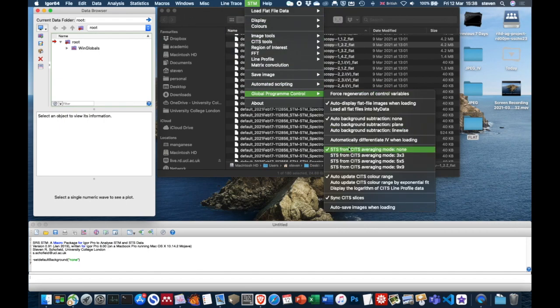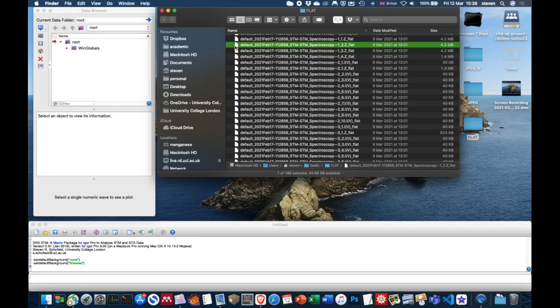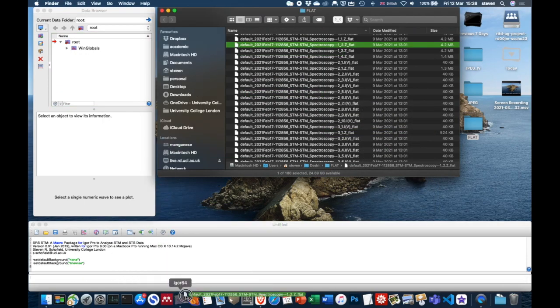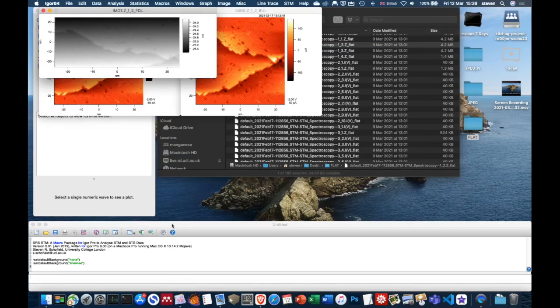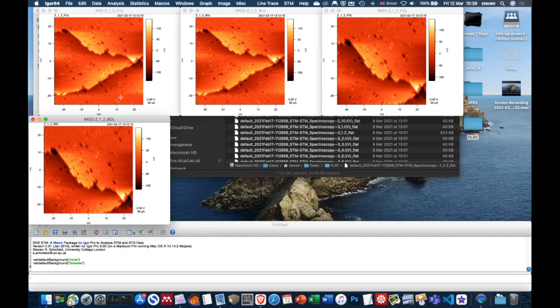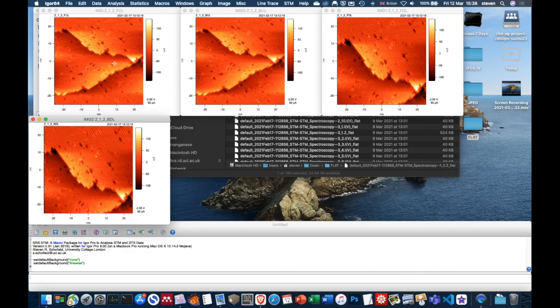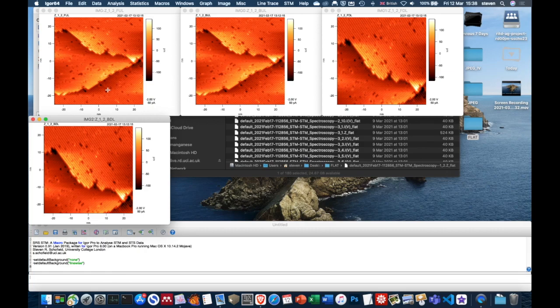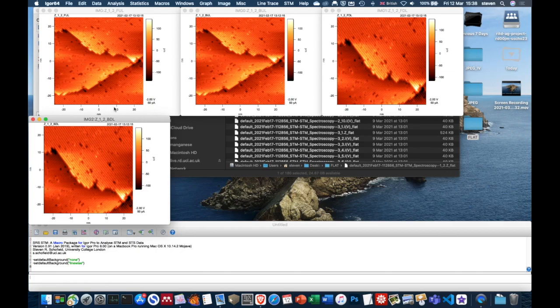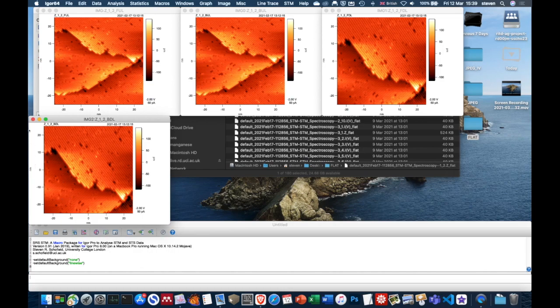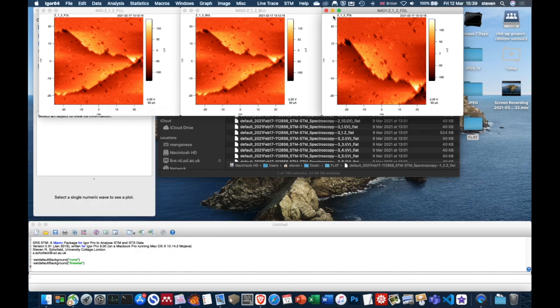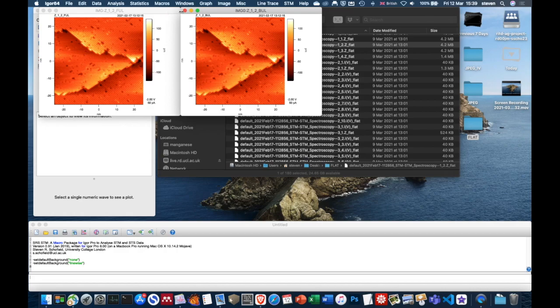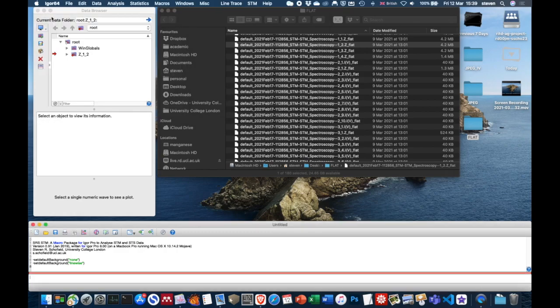Conversely, we could also have set that to global program control, auto background subtraction. If we make that line wise, then it will do a line wise subtraction on your data. And the thing about line wise subtraction is that it now introduces artifacts into the image. You can see that this little corner of the terrace looks like it's higher than the rest of the terrace. And that's just because what the program is doing with line wise subtraction is it's removing the background from each horizontal line as it goes. So the height information in the Z direction is now no longer really valid anymore. So it introduces artifacts into your data. But on the other hand, if you have data that has a lot of curvature to it, then sometimes it's nice just to run the line wise. You have a better chance of actually seeing the information in the image if you run the line wise subtraction. But when you're doing the detailed analysis, you're much better using a plane subtraction.